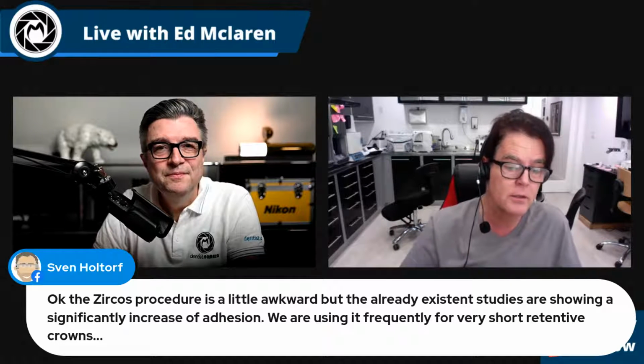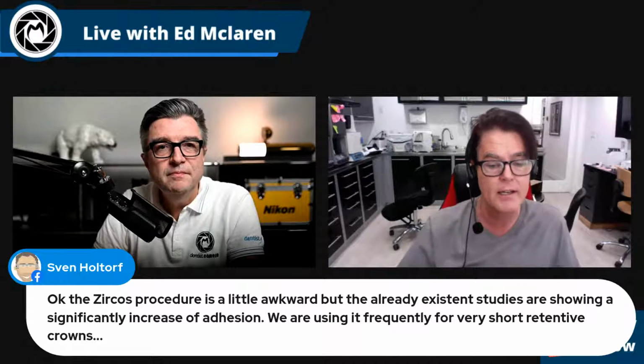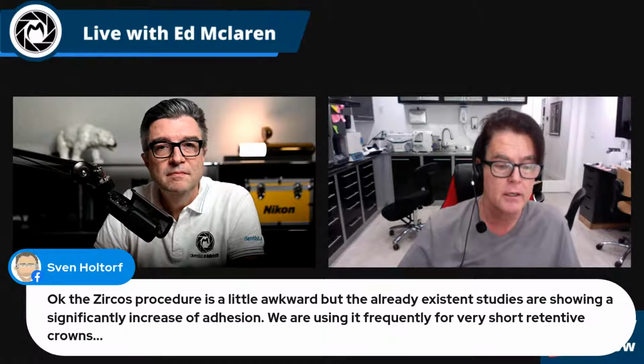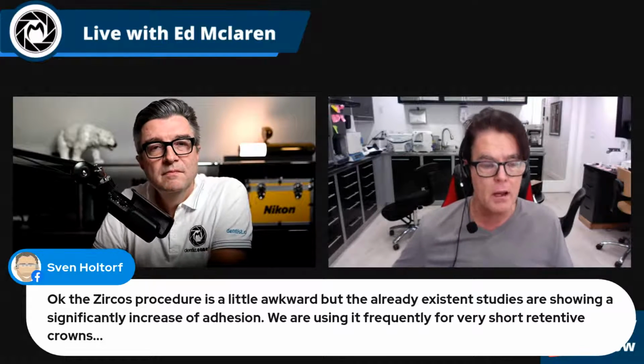He's already showing studies of increased adhesion. And the study UCLA did, they didn't show a gigantic increase in adhesion initially. But these materials in the mouth are susceptible to moisture. MDP primer can break down a little bit if there's excessive moisture. So I agree with Sven. If I was doing a more purely adhesive restoration, I would potentially look into that since it's available for us today. If you have macromechanical retention in your preparations, your retention and resistance form, you don't need it. Okay, so that's super cool.